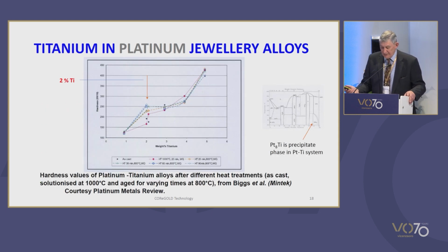graph from their publication. The patent gives many possible compositions including a preferred one with a 2% titanium addition and one at 950 fineness with a 2% titanium plus 3% of precious metal. It is not clear whether this work has been developed into a commercial 950 fineness platinum alloy, but clearly shows a lot of promise.